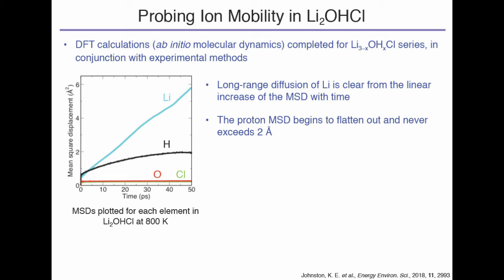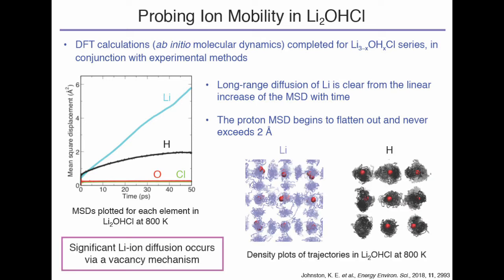So the oxygen and the chlorine have flat lines, they're not moving at all. The proton starts increasing but then flattens out and never really goes past 2 angstrom. And then the lithium, you can see, continues to go up and up and up, indicating that you have lithium diffusion within these materials. When you look at these density plots of the trajectories, they can actually see the movement of the lithium when they zoom in on the figure, and you can see it happening via a vacancy. That's different to the proton, which just sits at this localized point and doesn't move between the species there.